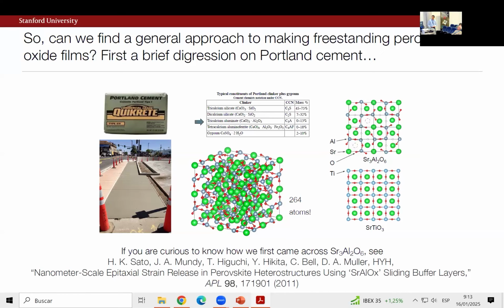The way we came about this was, just as an aside, as nicely mentioned in the introduction, we for many years have been looking at this lanthanum aluminate strontium titanate interface. And we wanted, for various reasons, to be able to use a perovskite building block for some of these different polarity interfaces. And we tried to make or metastably make a few unit cells, 1 unit cell of a perovskite equivalent of this.